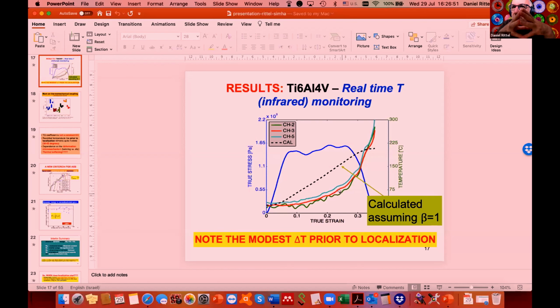It's not only microstructural and it's not only thermal. It depends on where your material fails. For instance, if you take a very strong steel, like maraging steel, it's very strong, but the failure strain is of the order of, say, 10%. It generates shear bands. You cannot expect a significant homogeneous temperature rise with a limited deformation of 10%.